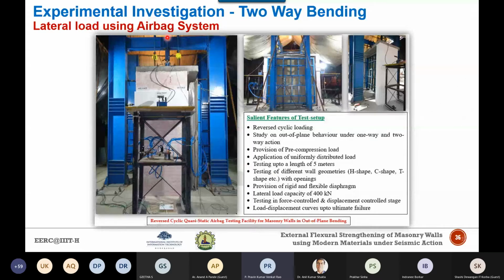Here you can see this backing frame, and just beside this particular backing frame, 6 airbags have been applied. This backing frame is placed very close to the wall so that the airbags inflate and apply a uniform thrust, in the form of a uniformly distributed force, to that masonry wall, so that the masonry wall will fail in the out of plane lateral direction.